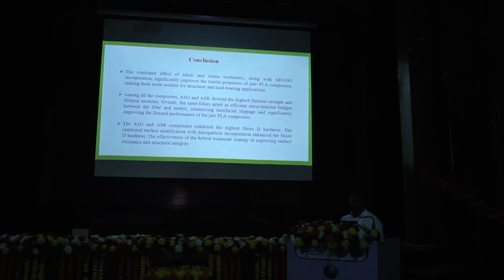applications. Among all the samples, the ASG and ASR samples showed the highest flexural strength and flexural modulus overall, the nanofiller act as an efficient stress transfer between the fiber and the matrix, minimizing slippage and significantly improving the flexural property of the jute PLA composite.